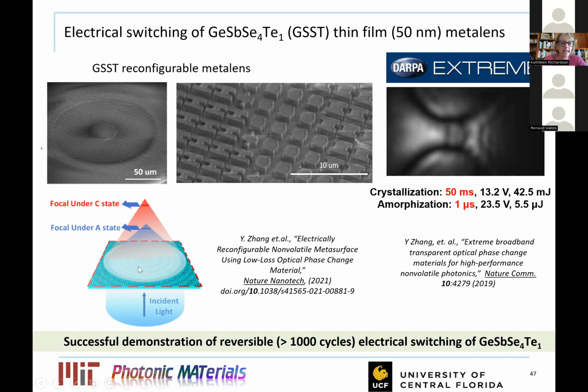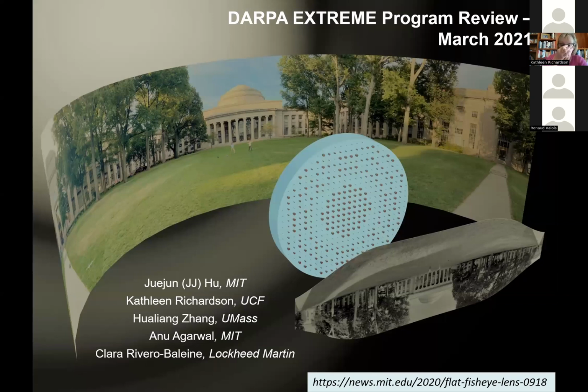Now, here's a static amorphous versus crystalline state. You can appreciate now if I can tune to someplace in between, we can now make a variable zoom structure. And that's exactly what we did as a result of this program. If you're interested in this, here is a demonstration of an imaging device. Shown here is the MIT campus. What was special about this is depending on whether we were in a micro or a macro focus scale, we showed that we could switch between a very narrow field of view to a very broad field of view.